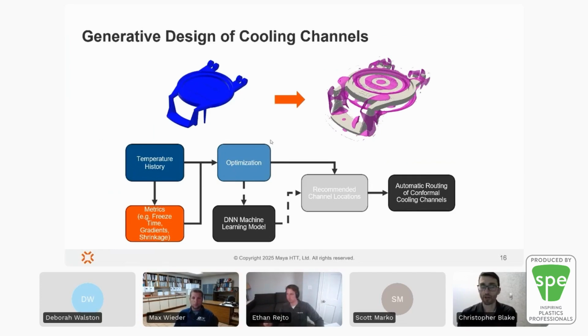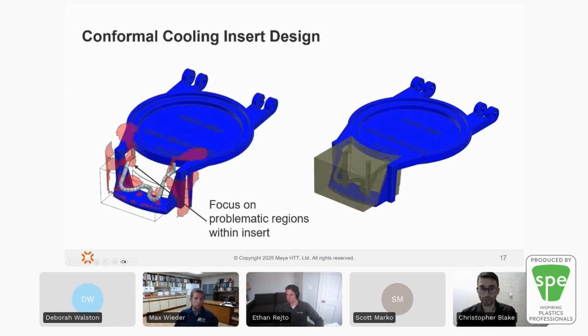So using SimForm, we can actually provide just the 3D CAD of this snap lid and have the software recommend the most important regions where cooling channels need to be located using an optimization routine. And we're working to add other accelerations to this process using AI. So here in the right-hand picture, you see for the snap lid in pink all the regions that were recommended by the algorithm where channels need to be located and to ensure more uniform temperatures on the part at ejection time. If we overlay the recommended regions on top of the insert, we see where the cooling channels need to actually be placed to get that more uniform surface temperature.